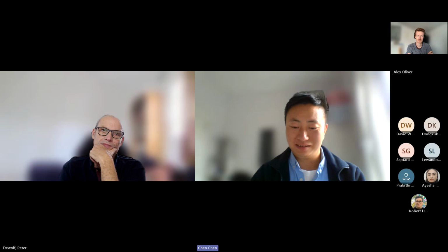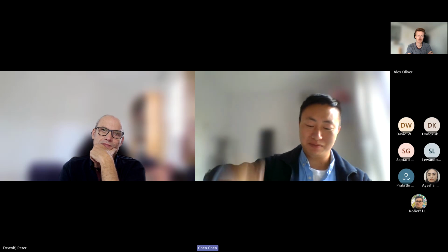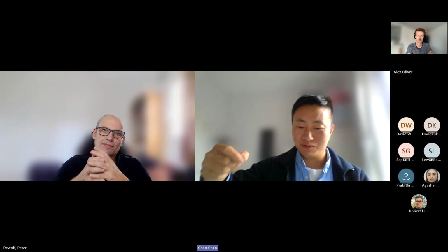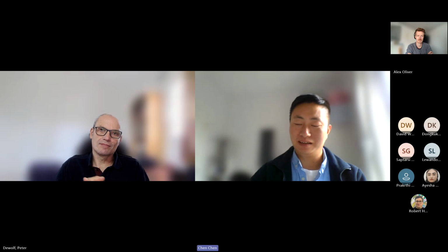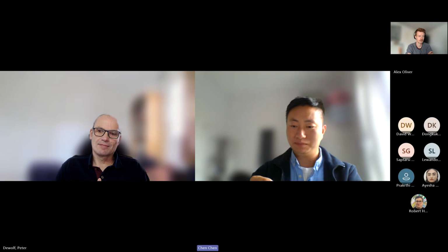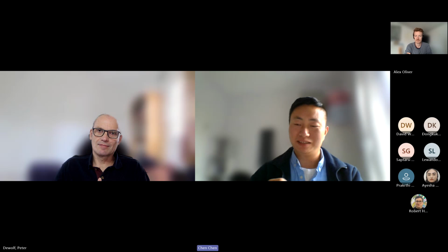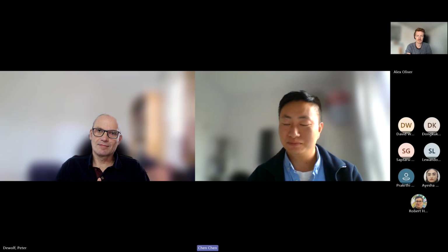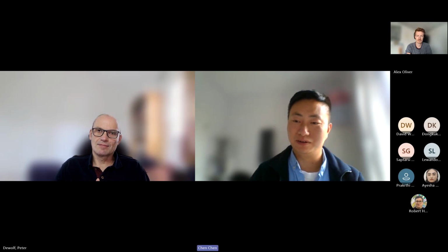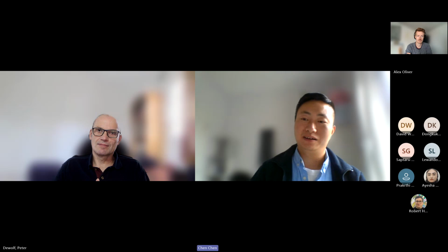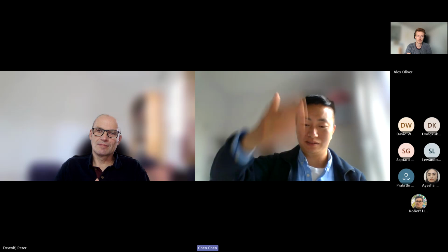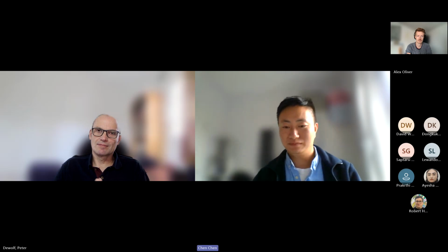So in my thesis, I suggest that when we smash the hammer, there will be a very big and sharp force or strain accumulating at the hitting point, and it needs to be released. To release that, it will naturally follow the natural crystal plane of our gallium nitride. That's why we always get a cross section which is the M plane.